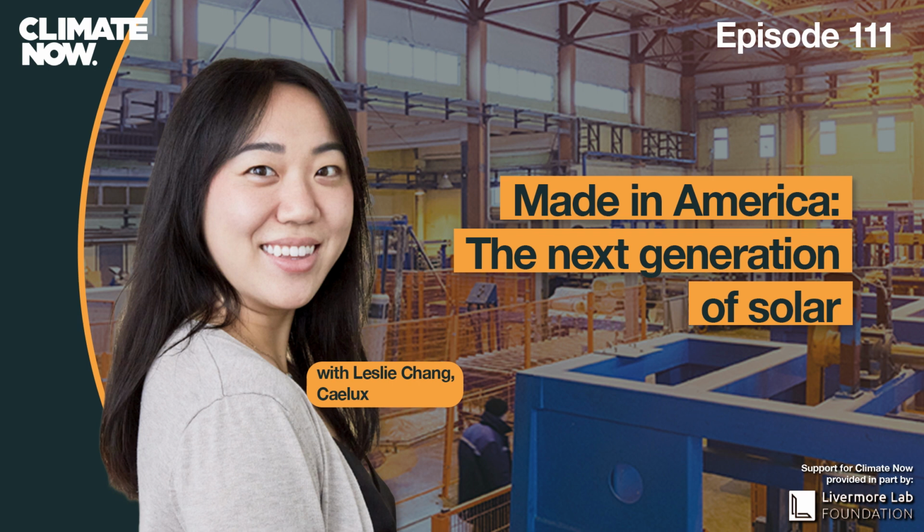Okay. And so there's no diminution in the amount of energy that can be produced by the underlying crystalline silicon layer? So the perovskite layer is semi-transparent. So there's a little bit of light filtering involved here. And just to go into a little bit more of the science behind it: perovskites capture high energy light. If you think about the visible light spectrum, there's a whole rainbow of colors, right? Perovskites capture the blue chunk of that spectrum, whereas crystalline silicon captures low frequency red light.